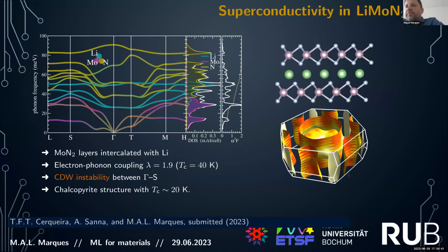Although the material structurally is two-dimensional, the Fermi surface also has three-dimensional components. The Fermi surface is pictured here. You can see in the center, there is actually a part of the Fermi surface that is three-dimensional, while there are still some parts that are two-dimensional. And this is what led theorists 20 years ago to say that this material was not interesting for superconductivity, because the opinion at that time was that you required an absolutely two-dimensional Fermi surface in order to get a good superconductor.